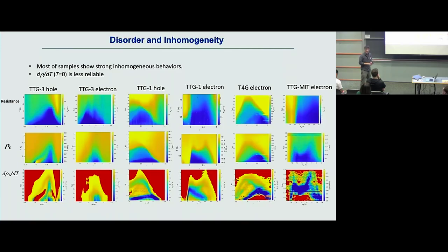But one thing that I can state is that if I choose the samples where I'm clearly seeing that there is lesser disorder in the phase diagram, I always do see the linear sloping down. If I go to the disordered regions of many samples, I see that it's not necessarily sloping down. It was rather flat, right? So at least I can see, throughout the samples, the correlation between the disorder and these d rho dT slopes.